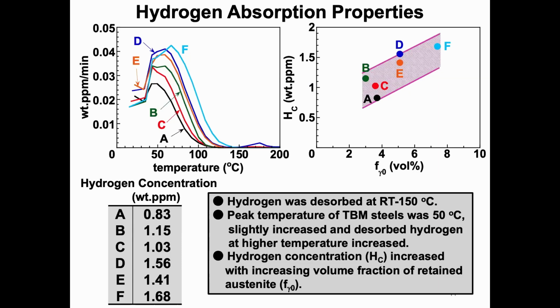And alloying element addition increased the peak temperature. And a high amount of desorbed hydrogen was observed in the TBM steels with alloying element. From the right-hand side graphs, we can see that hydrogen concentration increased with increasing volume fraction of retained austenite. This result suggests that a large amount of hydrogen is trapped in or around retained austenite.